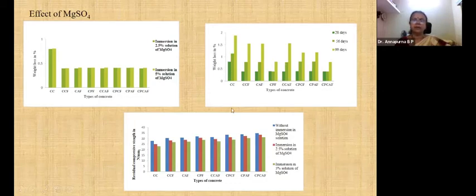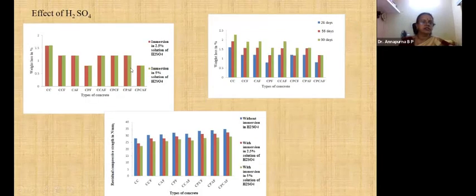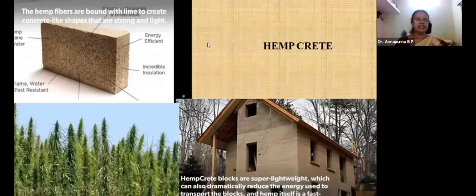So this is weight loss for magnesium sulfate immersion at 2.5% and 5%. Both 2.5% and 5% are studied here. This is the residual compressive strength after immersion. Sulfuric acid also shows a lesser loss in strength. So the residual compressive strength in concrete with different fibers is more compared to the conventional concrete. Next is the hempcrete, which I showed you.